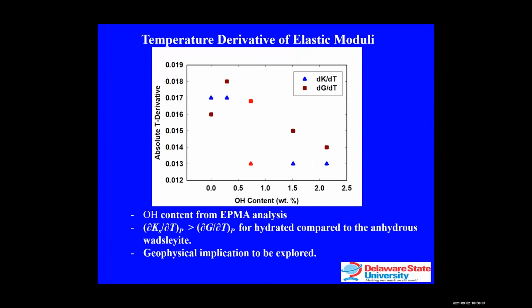Here we plot the temperature derivative of the bulk modulus and the shear modulus as a function of the water content. We're looking for this pattern, and you can see that the first data is from the anhydrous wadsleyite that we measured. Then the second one is for the 0.3 weight% water, and then subsequently other water contents. Again, the brown symbols are for the hydrated phase, and it shows that temperature actually affects the bulk modulus more than it affects the shear modulus. You can see from the data.